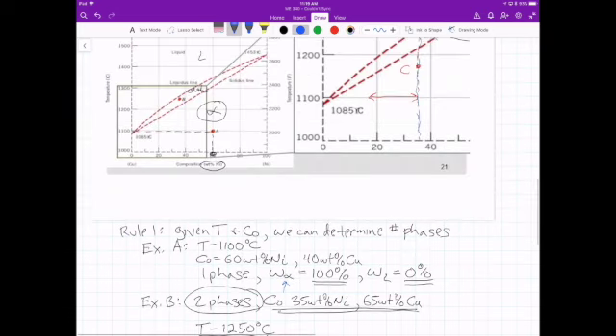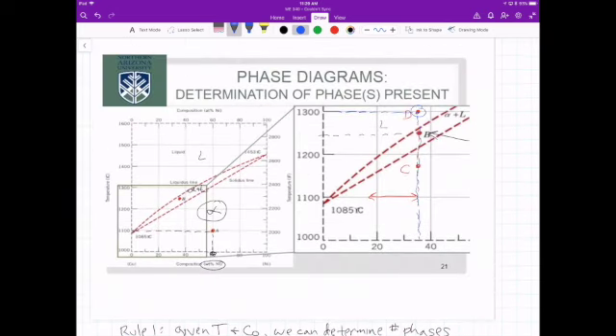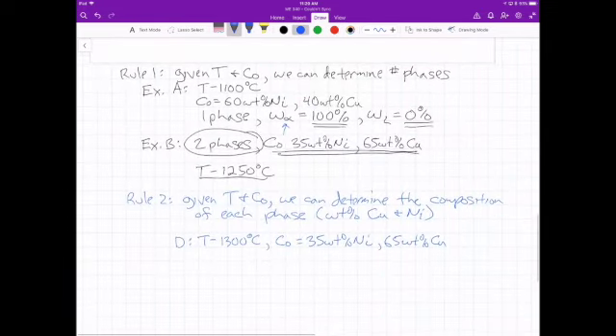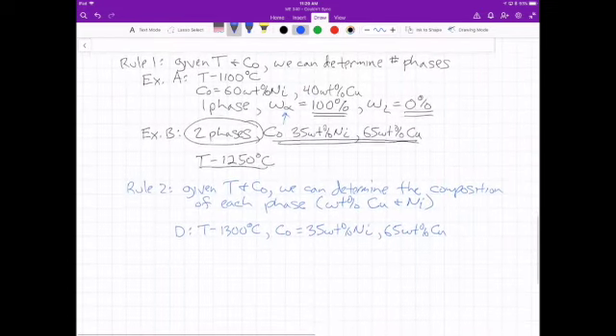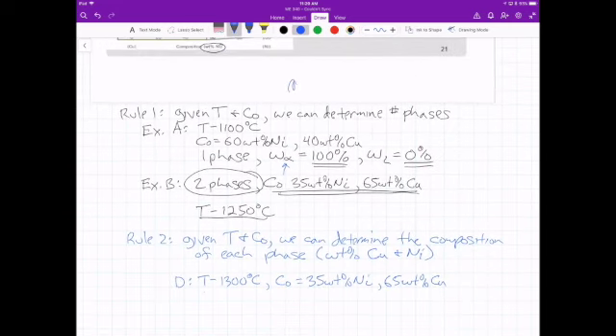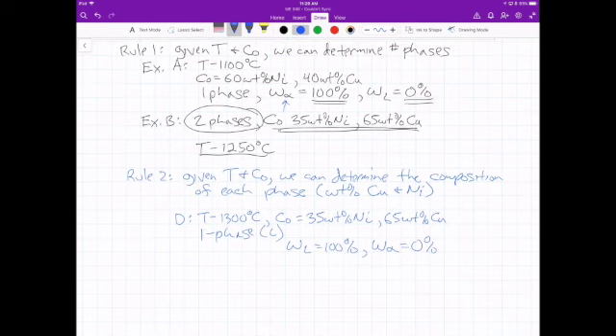How many phases exist at this temperature? We're in the liquid phase region, so we have one phase. That phase is all liquid. So if we're going to do weight fraction, the weight fraction of liquid equals 100%. The weight fraction of solid would be what? 100 minus 100 is 0. So there's no solid at this temperature. If there's only one phase, then my initial concentration also equals the composition of the phase.